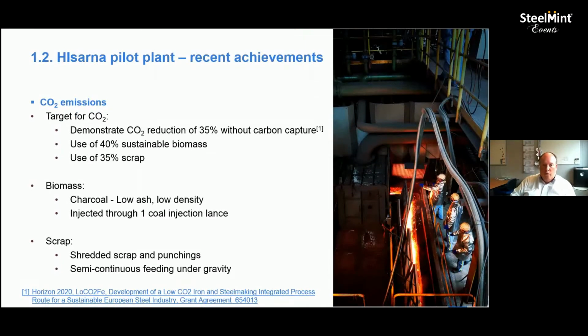So after the major revamp of the installation, we ran a project that was specifically targeting CO2 reduction, where we had to demonstrate 35% CO2 reduction without carbon capture technology. And we attempted to achieve that by using 40% sustainable biomass in the form of charcoal and 35% scrap. For the biomass, we used a low ash, but also low density charcoal, and it was injected through one of the coal injection lances.